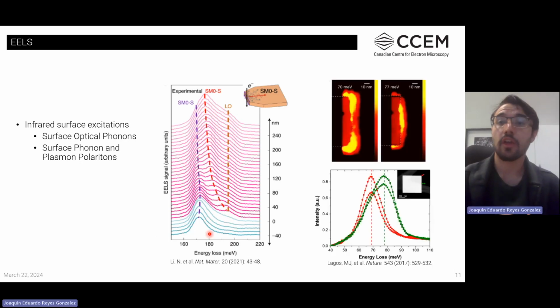Another example of what we can do with spatially resolved STEM EELS is investigating surface phonons of ionic material. Here we have the example of a magnesium oxide cube, where we can observe two different surface phonon polariton modes associated with the corners and the edge of the structure. So we can make that association of properties and structure.